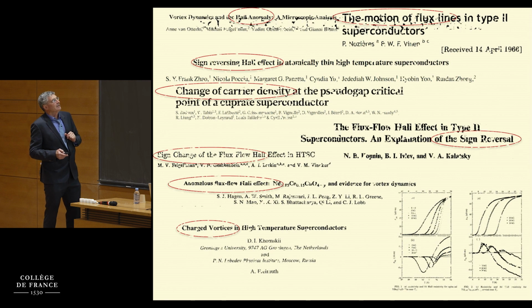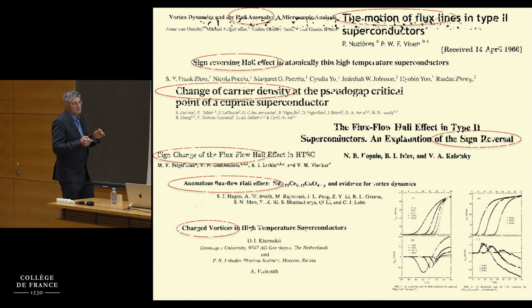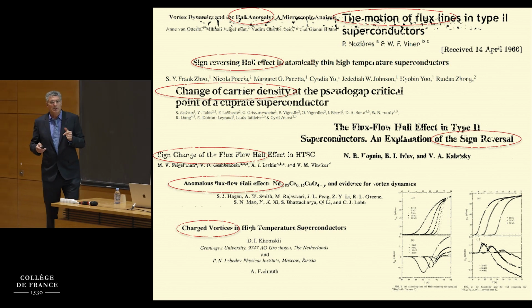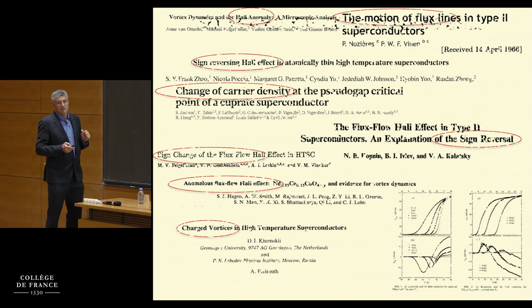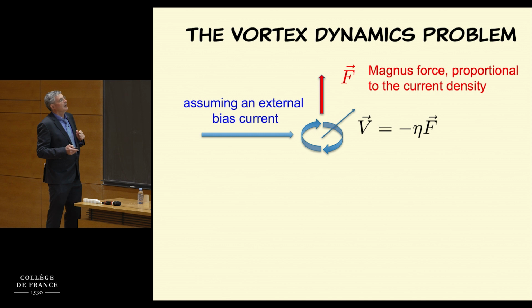So I'm just showing a small sample of the papers written by very well-known experts. And the Hall sign change in different systems acquired different theories. But actually, it seems to be quite a universal phenomenon close to TC. The problem I'm writing here is not so much the problem of the experiment, but the problem of the theories that use vortex dynamics. What's the problem with vortex dynamics?